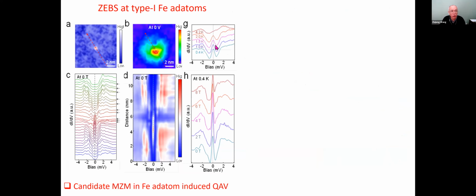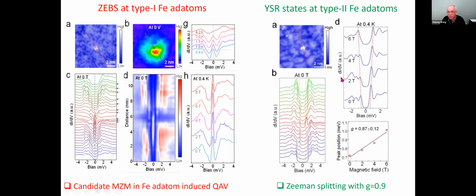Okay, so a closer look at this shows that the type 1 atoms will have this zero energy bound state. What's really interesting is if you do a map of the zero energy state, you see this candidate Majorana zero mode peaks away from the magnetic ion, which is a little circle. So this off-centered Majorana mode, I'll come back in a bit to explain. And these other type 2, if you add a magnetic field, they actually split, giving you a g factor about 0.9, very reasonable. So it's comforting to see both. You do see Yu-Shiba-Rusinov states, and you also see zero energy mode, presumably due to the vortices induced.